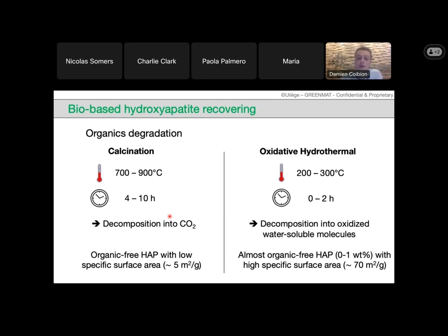And we can do it without dwelling time or with a dwelling time of 2 hours, so in a shorter time also. So we recover an almost organic-free hydroxyapatite. We have less than 1 weight% of organic matter inside. But compared to calcination, we recover a high specific surface area, close to 70 square meter per gram.